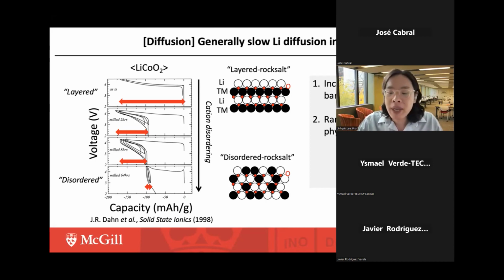Note that based on this understanding, people have been trying to avoid any kind of cation disordering in the layered structure, which leaves us no choice but to use both nickel and cobalt, because there are very few possible metals that can actually stabilize the layered structure with a reduced amount of cation disordering for fast lithium diffusion. So overall, these DRX materials have been considered poor lithium diffusion materials, so they have been neglected as a cathode for a very long time.